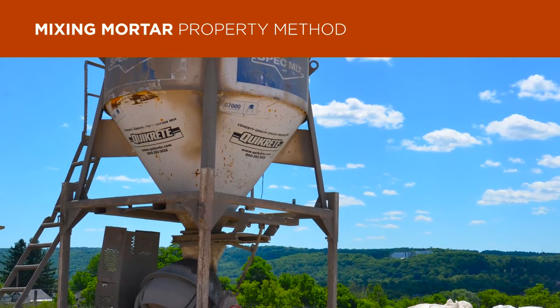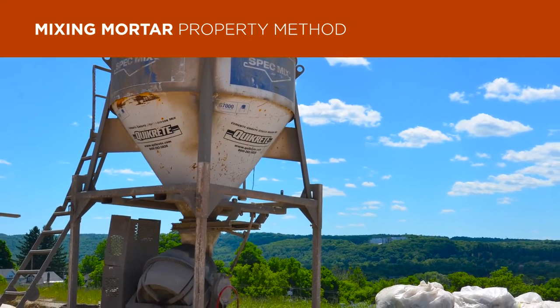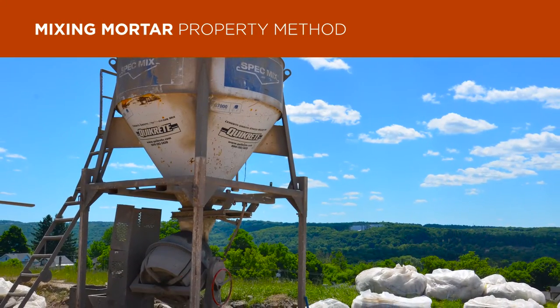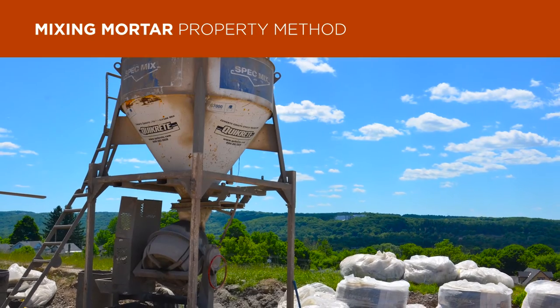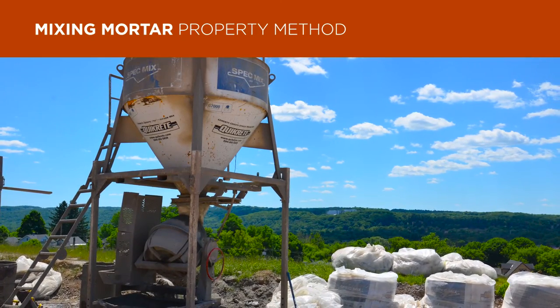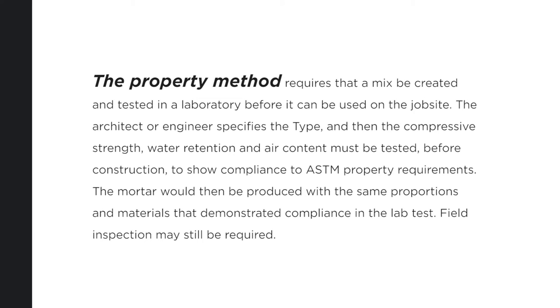While premixed mortars that contain the cementitious materials and aggregates already blended together in the bag can be produced in the factory using the proportion or property methods, most use the property method and require testing. The property method requires that a mix be created and tested in a laboratory before it can be used on the job site. Architect or engineer specifies the type. The compressive strength, water retention, and air content must be tested before construction to show compliance to ASTM property requirements. The mortar would then be produced with the same proportions and materials that demonstrated compliance in the lab test. Field inspection may still be required.